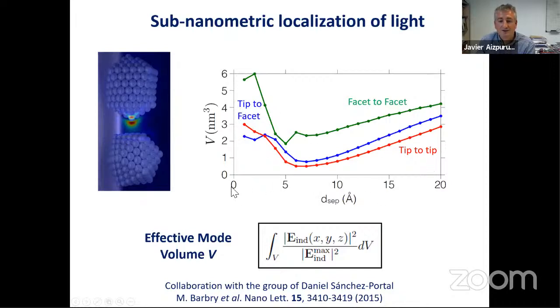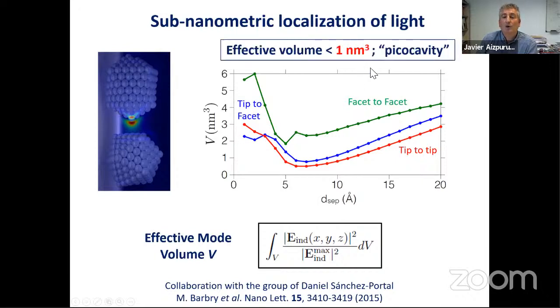And as a function of separation distance, they plotted the effective mode volume of such a system. And they saw that the effective mode volume of this kind of cavity can be smaller than 1 cubic nanometer. This is the extreme example of an optical cavity because it's below a nanocavity. We call it, maybe abusing the language a little bit, a pico cavity.